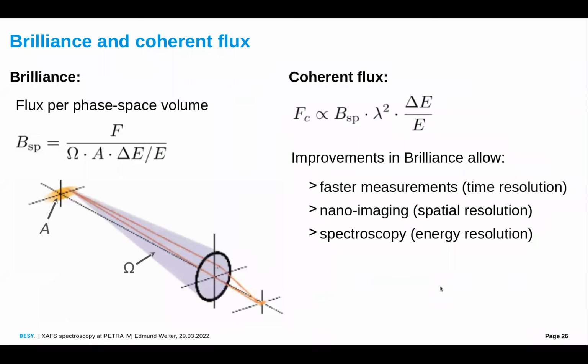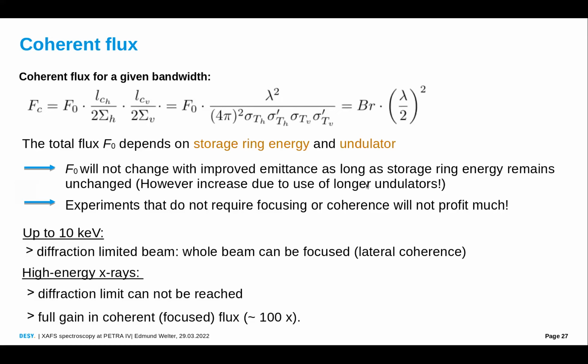Brilliance and coherent flux, very briefly, because otherwise I will run out of time. Let's start with the flux. The flux of an undulator, for a given undulator and a given storage ring with a certain stored current, is the same. It will not change. So we don't gain much in flux, but we gain in brilliance because the cone of the beam becomes smaller. The coherent flux is proportional to the brilliance of the beam. So if we increase the brilliance, we automatically also increase the coherent flux. And so the total flux will not change much due to the improved emittance.